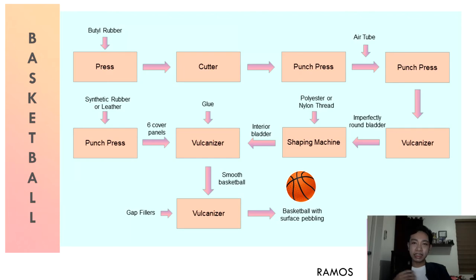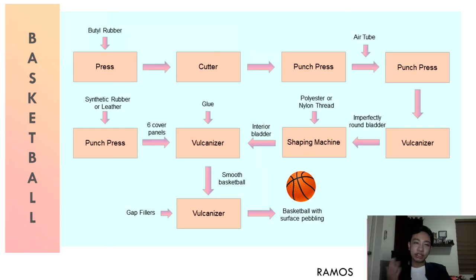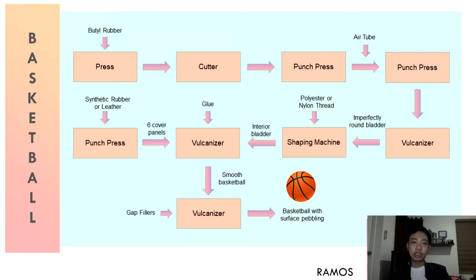The air tube is manually inserted by hand, and the piece is sent to another punch press that stamps rounded edges and binds them. The interior bladder is then sent to a vulcanizer that heats the rubber under pressure to make it more flexible and durable. The bladder is also inflated in the vulcanizer, and if it stays inflated for 24 hours, it passes the initial testing stage. The bladder is then sent into a shaping machine which wraps polyester or nylon thread around it to create its spherical shape and prevent deformation.